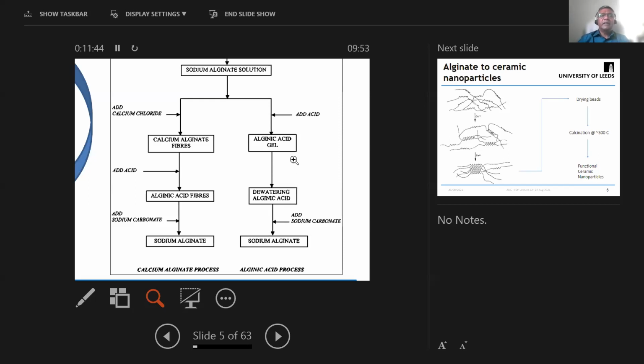The acid treatment is similar, but this particular step is eliminated, so directly you get alginic acid. Sodium alginate is treated with mineral acid to produce alginic acid gel, and then it is dewatered. So the water component of the alginic acid gel is removed, and that gives rise to a thicker gel, which is then treated with sodium carbonate to ion exchange the proton present in the alginic acid, for further purification to form sodium alginate. And this sodium alginate is then again used by the food and pharmaceutical industries or even cosmetic industries.